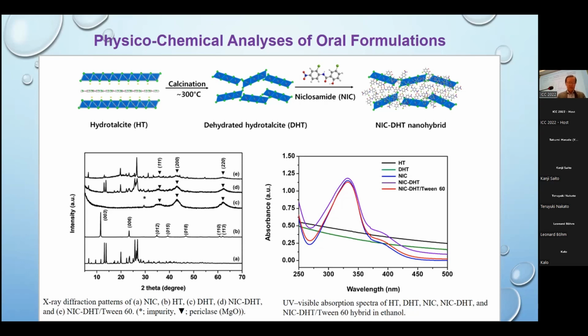According to the UV visible absorption analysis, as you can see on the right-hand side, we observe the characteristic peak of pure niclosamide in ethanol, and this characteristic niclosamide peak was retained in both NIC DHT and NIC DHT coated with Tween 60. As you can see here, no specific peak shift could be observed in the absorption band, indicating that the non-ionic polymer was coated on the surface of the anionic clay through simple physical absorption and was not chemically modified on the surface.